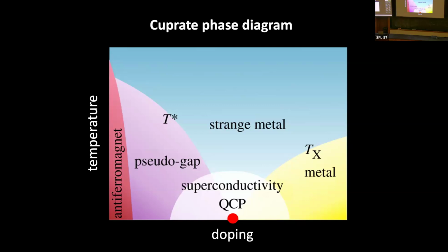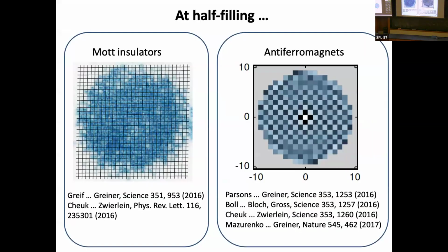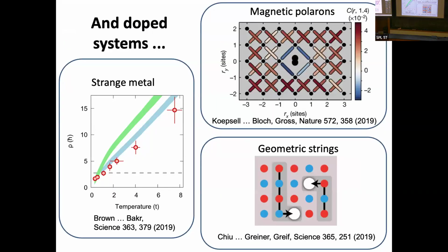And this is very unusual because in a system where the interactions between the electrons are the cause of the resistivity, Fermi liquid theory would predict that you should get a quadratic scaling of the resistivity with temperature. However, in the cuprates and many other correlated materials like bilayer graphene and so on, you observe this unusual behavior where the resistivity is linear, and that's something people still don't understand. And there was a question of whether the Hubbard model can actually produce this type of behavior. And indeed, we did these experiments in my group, and we found that indeed the resistivity is linear in temperature.